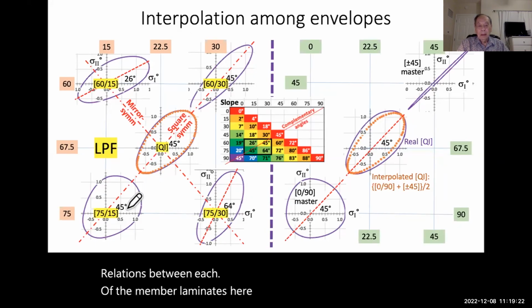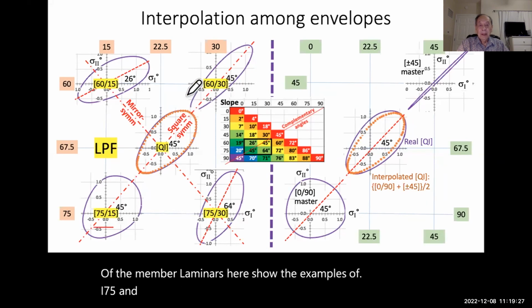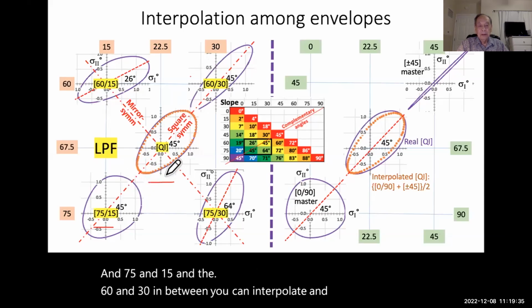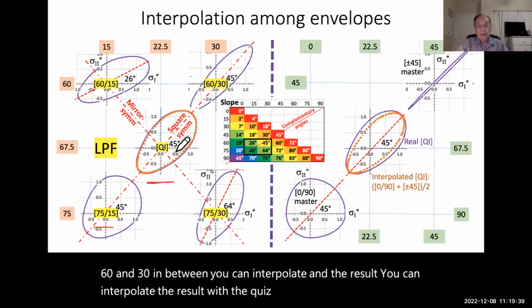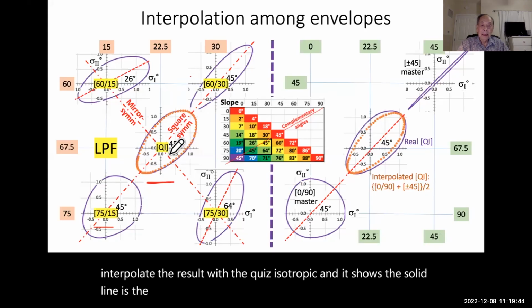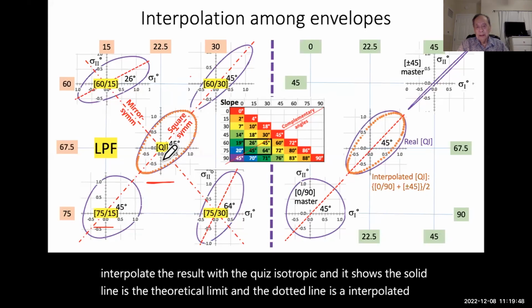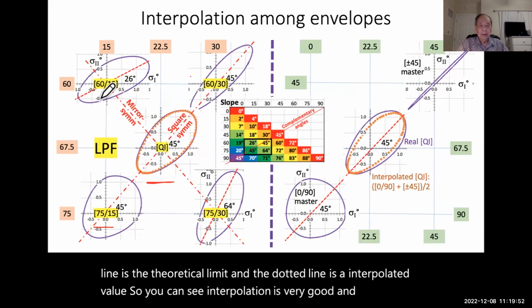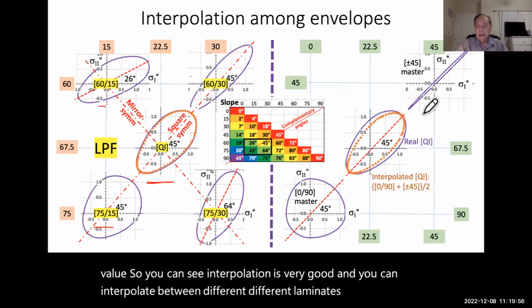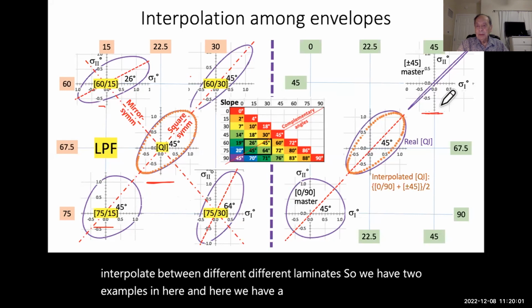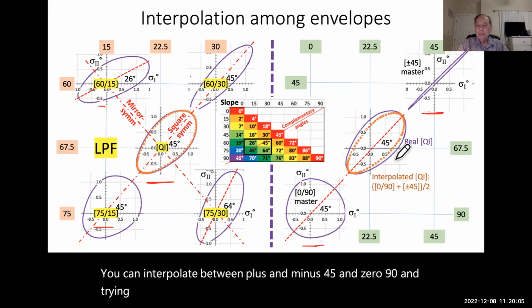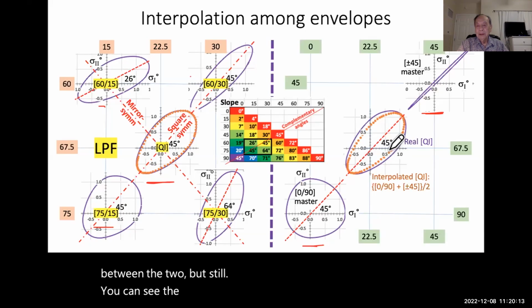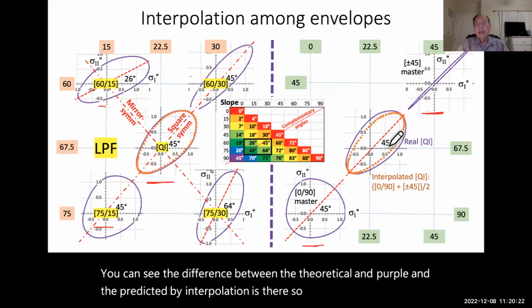Here we show the examples of a 75 and 15 and the 60 and 30. In between, you can interpolate the result with the quasi-isotropic. The solid line is the theoretical limit, and the dotted line is the interpolated value. So you can see interpolation is very good, and you can interpolate between different laminates. We have two examples here, and here we have a very extreme one. You can interpolate between plus or minus 45 and 0/90 to get the quasi-isotropic. This is quite a distance between the two, but you can still see the difference between the theoretical in purple and the predicted by interpolation. So it is something that is doable.